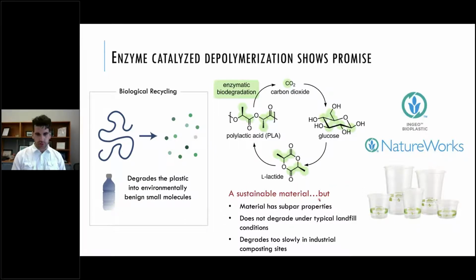So polylactide is a great sustainable material and obviously used. There are a few challenges for it, however. Unfortunately, the material has subpar properties. So honestly, if PLA had great properties, it would start to displace things like polyethylene, and that would really be great. But unfortunately, it just doesn't have those good properties, so that really limits its applications. Consumers don't want to use it for many things. Unfortunately, it's found that while it degrades in laboratory tests, it does not degrade under typical landfill conditions all that fast. So if you just put these things in a landfill, they'll still sit around for hundreds of years without degrading. So the rate of degradation is too slow.